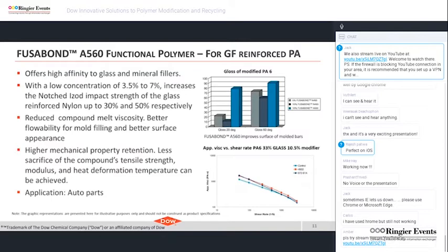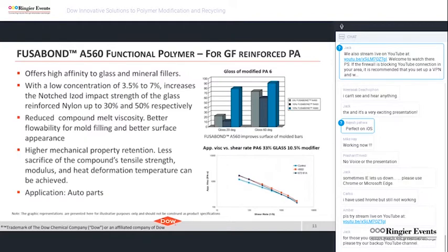Fusabond A560 offers high affinity to glass and mineral fillers. With a low concentration of 3.5 to 7%, it increases the notched izod impact strength of the glass reinforced nylon up to 30% and 50% respectively. The chart at bottom right shows apparent viscosity versus shear rate of PA6 compound with 33% glass fiber and 10.5% modifier comparing control, Fusabond N493 and A560.